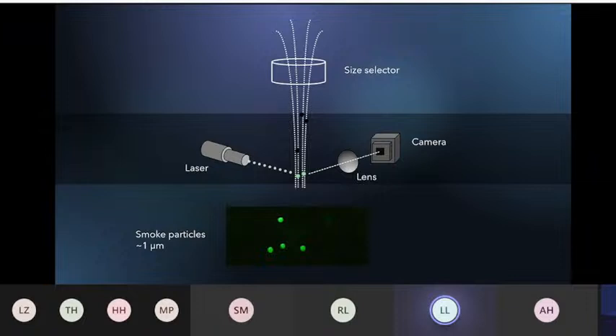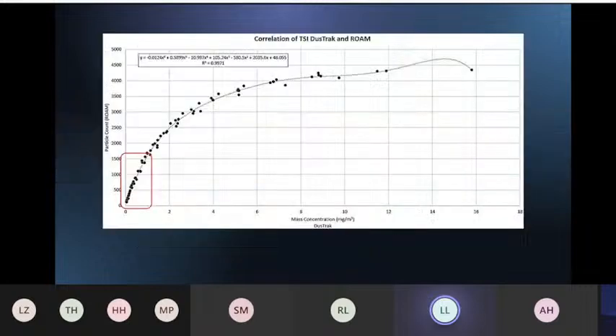The size selector, on the other hand, unlike current instrumentations that use Mie scattering, so instead of referencing a table for intensities related to particle sizes, we've just used a size selector so that only the sizes that are relevant to us are going to be counted. So right now it operates on PM 2.5. And though very simple, the technique is actually surprisingly efficient.